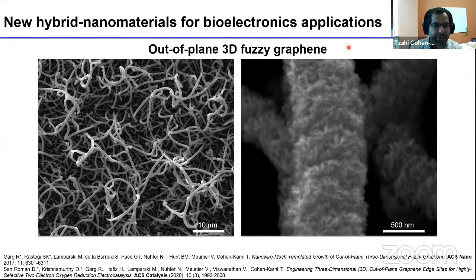So these are nano pipe brushes made out of a core that is a silicon nanowire, but again, the core could be any material that can sustain the growth temperature, which is several hundred degrees Celsius. And the bristles of the pipe brush are basically single to few-layer graphene flakes. So you can imagine that this structure has enormous surface area. And something really unique that we came across while working on this material is that it has really unique electrochemical and catalysis properties and optical properties. So just by growing this material, this actually opened up so many research tracks in the lab. I'll present a couple of them in this talk.